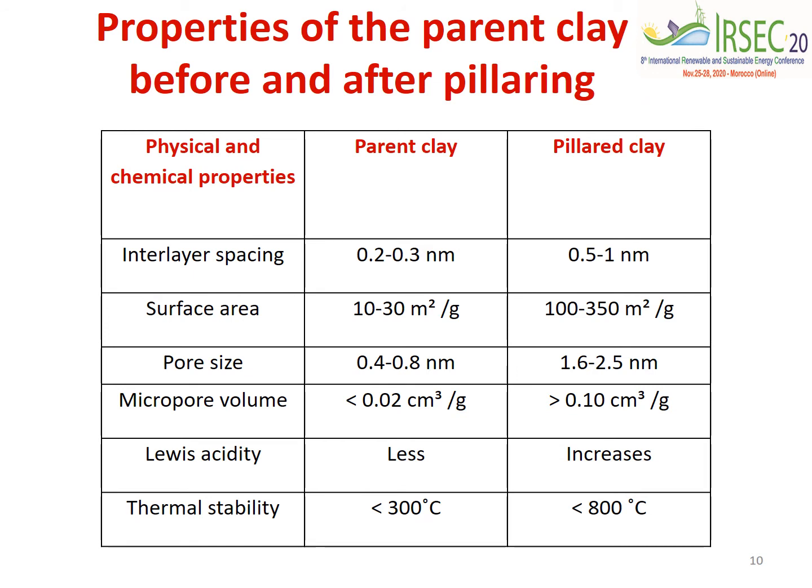These are the properties of parent clay before and after pillaring. We can see in pillared clay the interlayer spacing increases. Surface area also increases after pillaring. It's around 10 times. Pore size and micropore volume also increase, and in pillared clay we get more Lewis acidity and it is more stable.